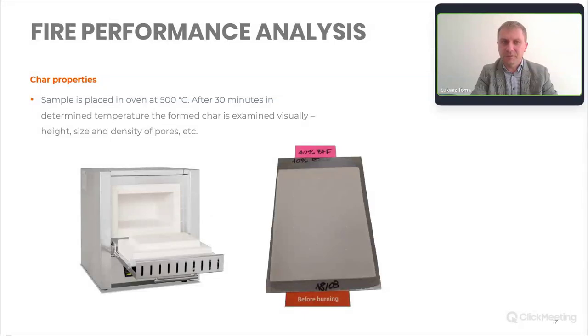And finally, we have fire performance analysis. To evaluate the intumescent effect, this kind of test is very simple, because to do this, we put the sample, which is applied on the steel plate, into the oven. Inside the oven we have 500 Celsius degrees, and we keep it for 30 minutes. And after cooling down to the ambient temperature, we can examine the char.